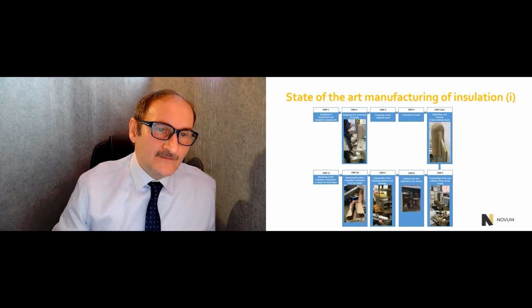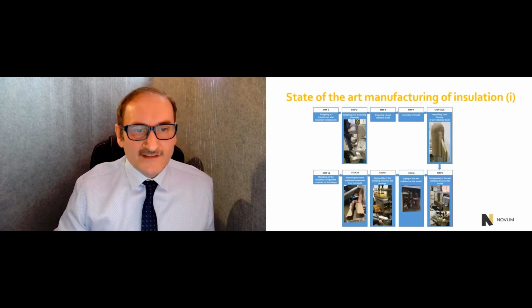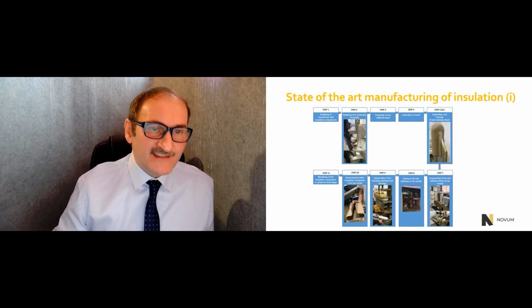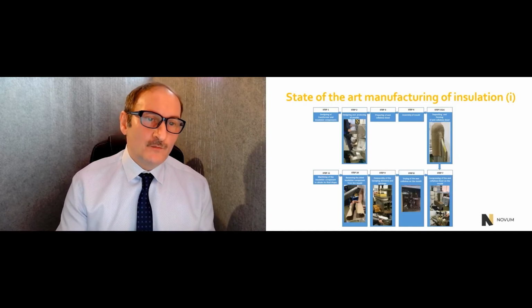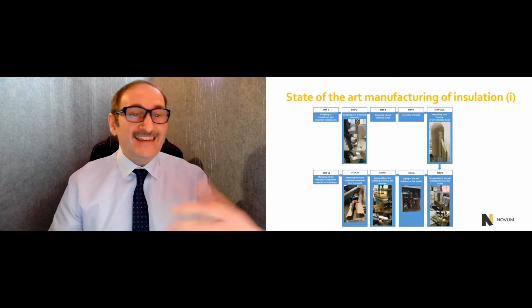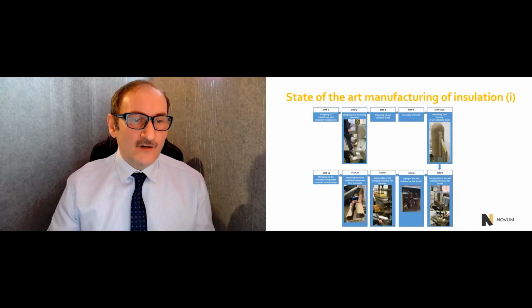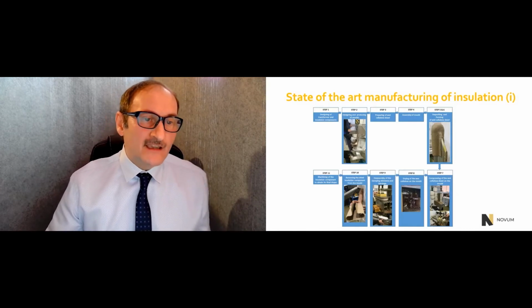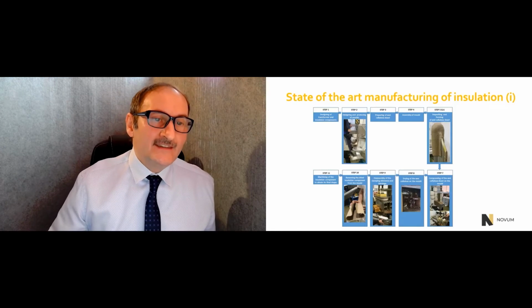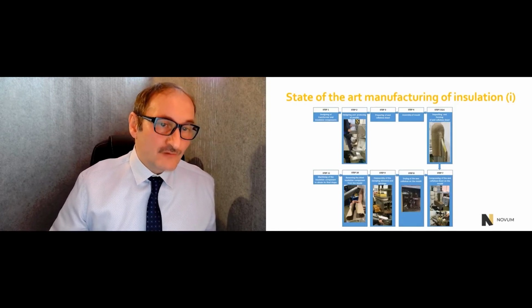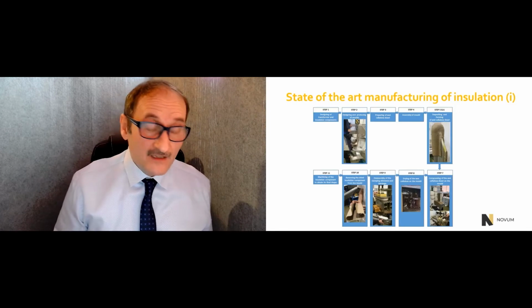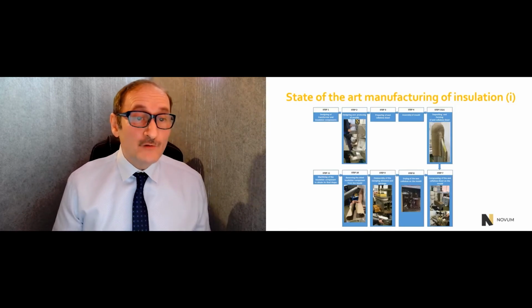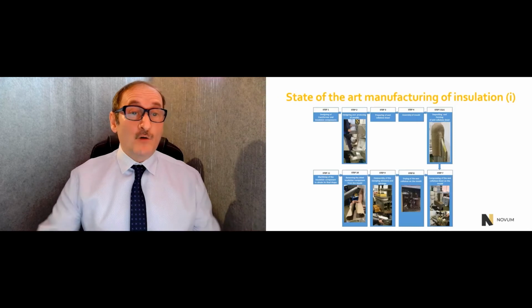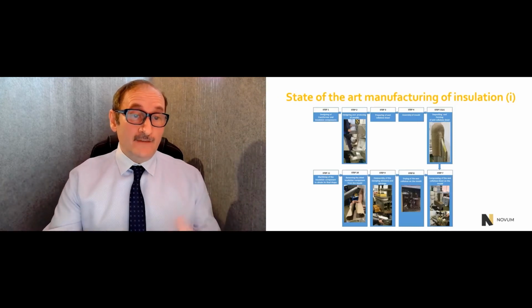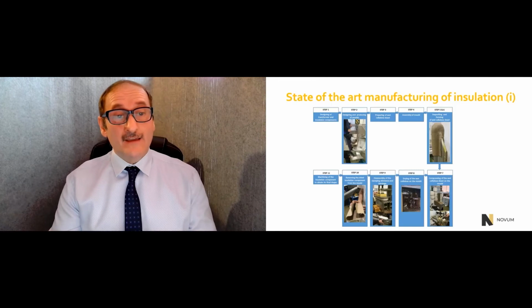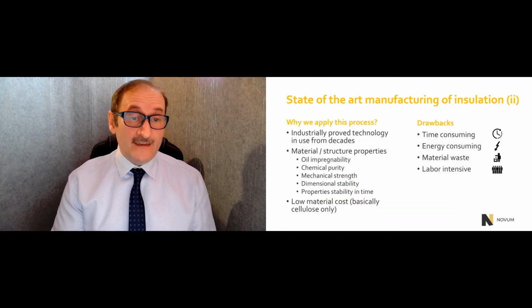Usually we are using wet cellulose pulp, and there are dedicated molds, and we sculpt the final shape on the mold. All this is many hours of manual operations to sculpt these thin shapes on such molds. After this deposition on the mold, of course, we have to use an additional clamping system to remove the moisture from the wet pulp. And after that, we have another very long-lasting and also energy-consuming process. Namely, we have to put the component in the drying oven. And usually you need 5, even up to 8 hours to evacuate the moisture from such a system. So altogether, if you add all these stages, we have a long cycle time and a lot of energy consumed.